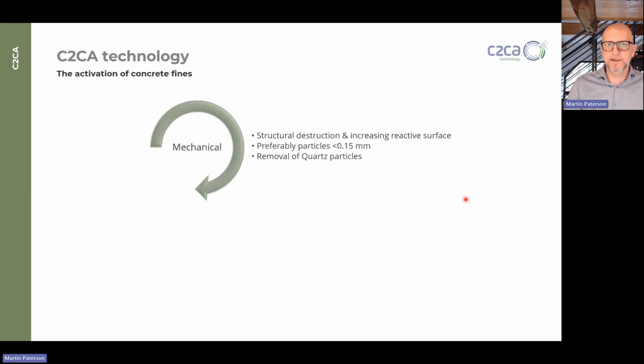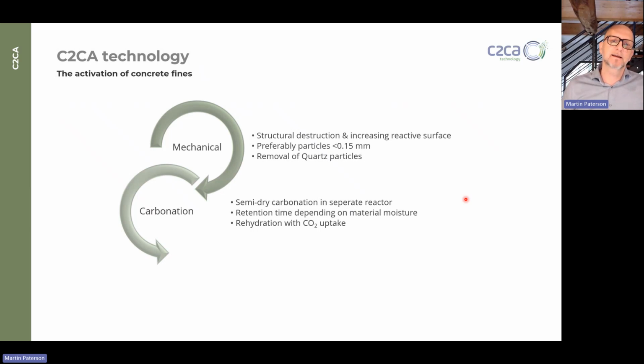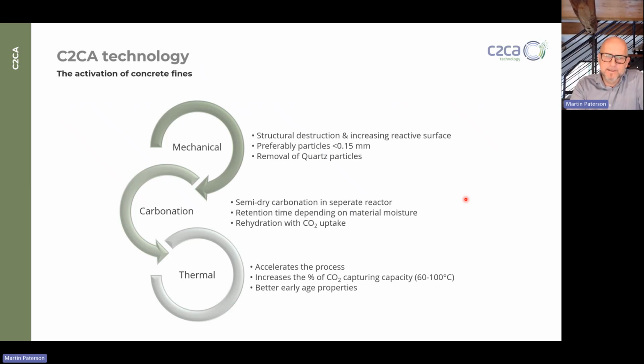As I said, the activation of concrete fines, a little bit more detailed. So first of all, we downsize it. Here it's mentioned 150 microns, but we rather go smaller. We also remove the quartz particles after the grinding. Then we carbonate it in a semi-dry process. The carbonation time depends of course heavily on the moisture of the material, but since it's almost dry, we need quite some time to do it. And the thermal treatment, since we're also applying low heat, it doesn't really affect the reactivity of the material, but it accelerates the process, and it increases the ability of CO2 being captured.